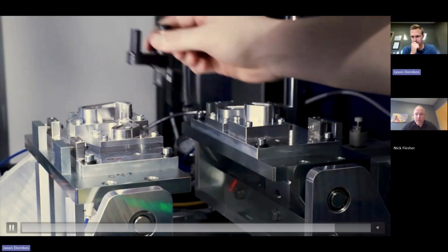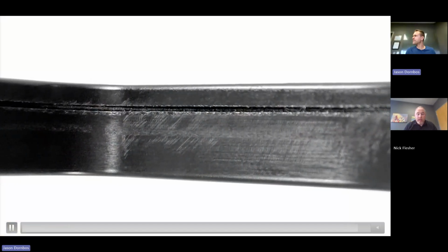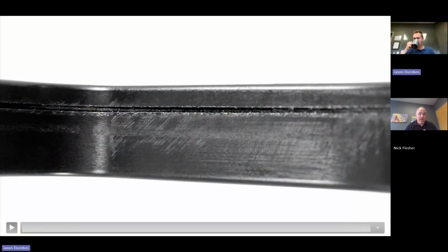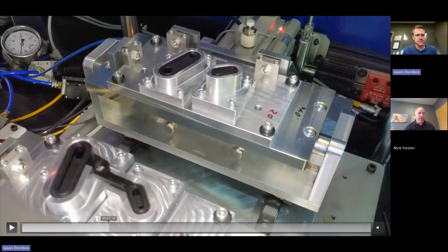Are there specific part design or material limitations that must be considered when using IR laser welding? Absolutely, Karina. You need to make sure that the plastic has the proper absorptive properties for the wavelength you're using. So, for example, for direct laser welding, 2 micron actually doesn't absorb that efficiently in plastic, but it's pretty uniform. And so you can get more color variation.